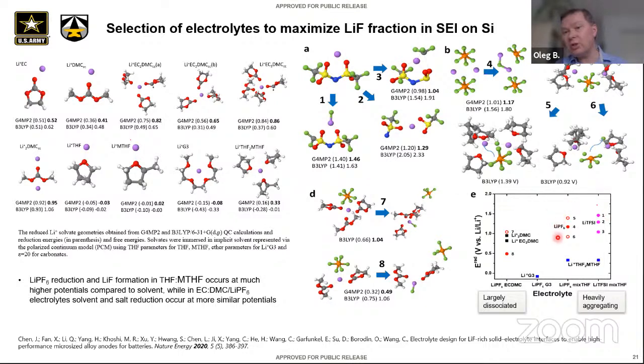So for that reason, LiPF6 was chosen, and Chunsheng Wang's group has shown that it performed great in terms of enabling macro-sized silicon with a Coulombic efficiency of 99.9%, right? So that's just one example of how we can use these very simplified calculations in order to choose the target SEI, right?